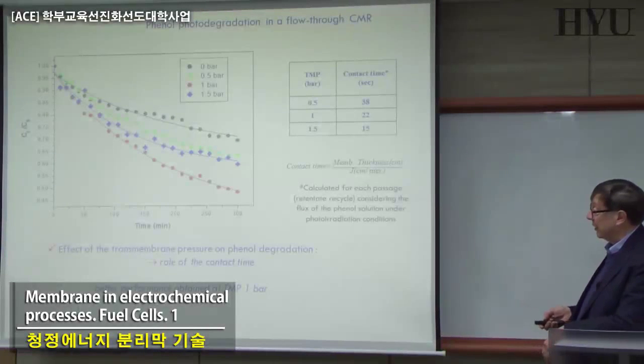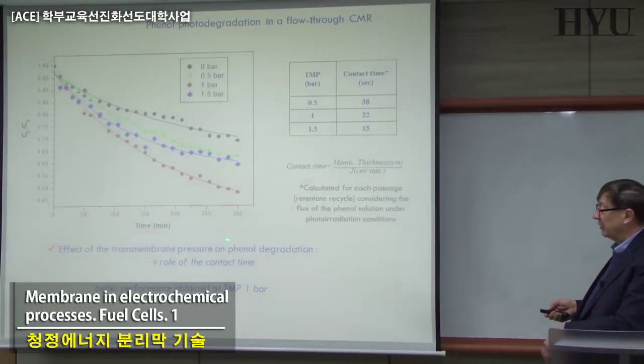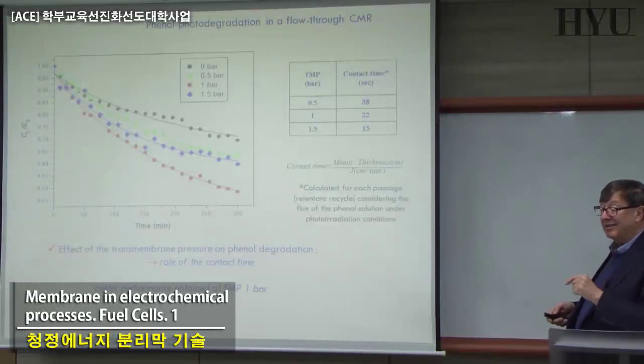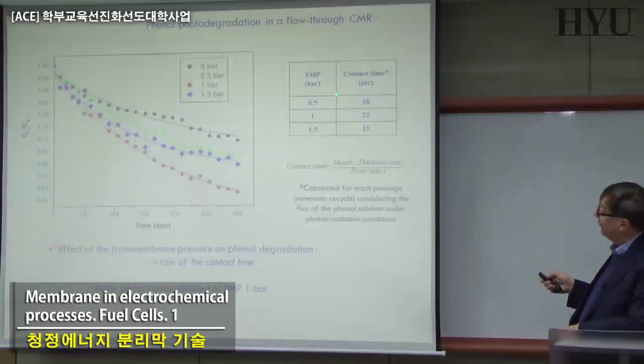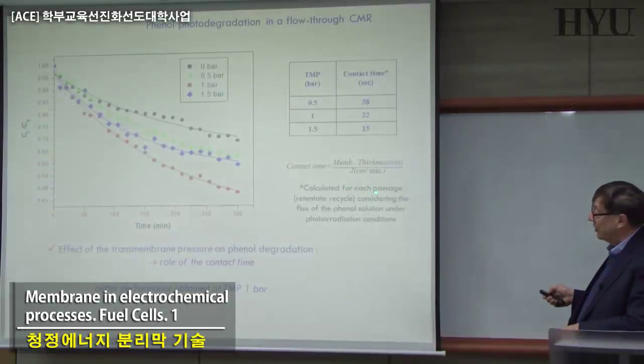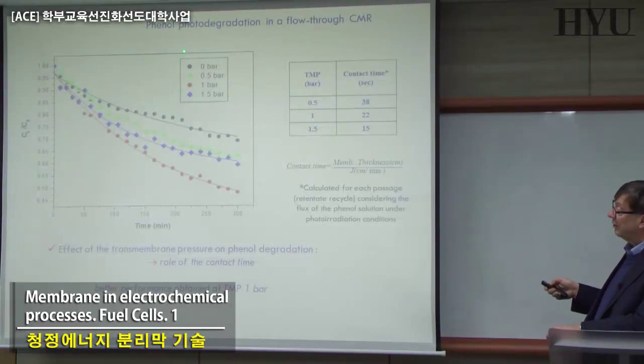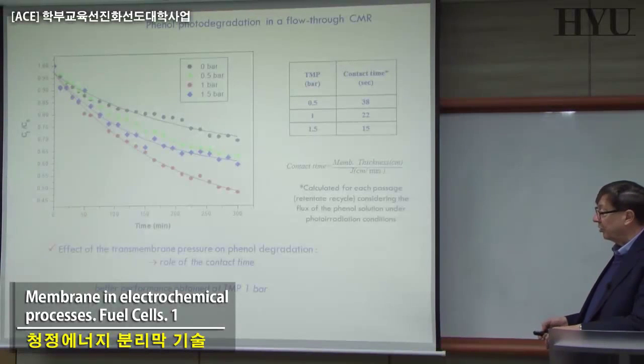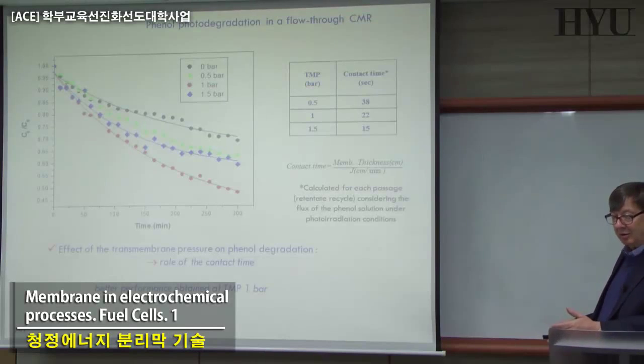And here are data that show the effect of the transmembrane pressure on the degradation. That means the contact time, which you can see here, as the transmembrane pressure increases. When you are increasing transmembrane pressure, basically what you are doing, if the system works, is decreasing the contact time. The permeate is moving faster, and you can see here that with transmembrane pressure from 0.5 to 1.5 bar, 38 is becoming 15, and if you analyze it, this is consistent with the experimental result that you obtain here. With this, the system just works, and also here you have to try to optimize. It's not easy to anticipate the results.